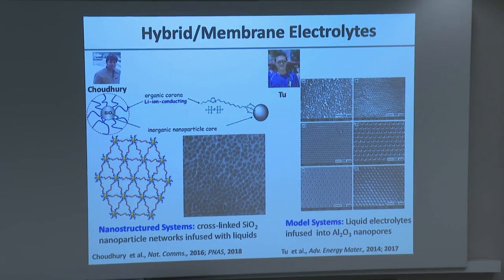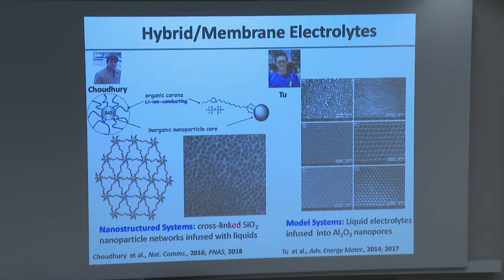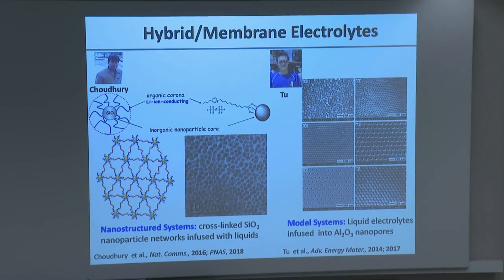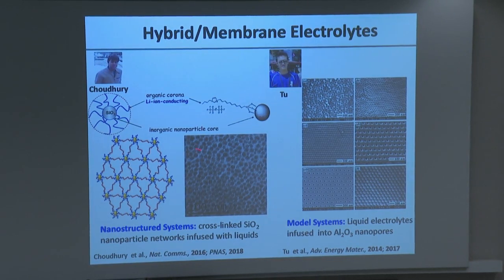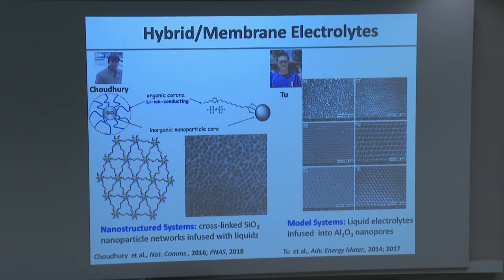So the end result is that you make plastic-like sheets, where these sheets have a secret, that they're porous. And this is what the secret looks like. So the black spots are the particles, so ions can't move through them. The gray spots are the empty spaces that ions can move through. And again, by controlling the number density of the black spots, I can control the gray space size. So I can control this length scale lambda, okay?